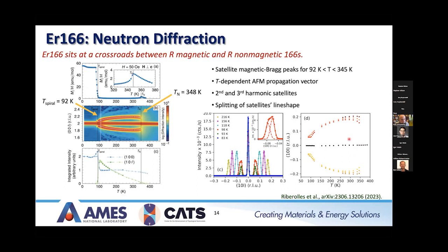That's plotted on the right here, where we show the center of each component versus temperature. You can see at high temperature, we need 3 Gaussians to describe the peak. And as we go to low temperature, you need 2 Gaussians. The splitting between the two satellites becomes narrower and then widens again with temperature, but you never see the third peak reappear.